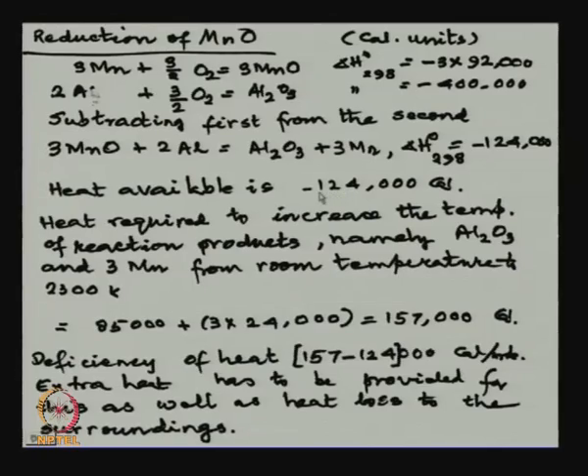So, this is the amount of heat being made available by the reaction, but if you look at the amount of heat required for manganese and Al2O3 to be heated from room temperature to 2300 K, it is this much. So, there is a deficiency of heat. We need this much heat to take the products up to 2300 K, but the reaction is giving us only this much. So, if we want to produce manganese by aluminothermic reduction of MnO, then we need to supply heat externally, otherwise the reaction will not be spontaneous.